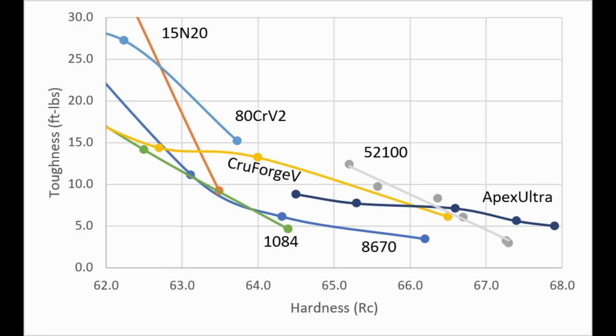I have a separate article on how to heat treat 80CrV2 and Cruforge V if you're interested in how to heat treat those to 64 Rockwell. I need to do an article on 52100. I don't have anything on how to do high hardness heat treatments for it, but you can see that around 65 to 66, 52100 looks great, but it does start to fall in toughness beyond about 66 or 66.5.